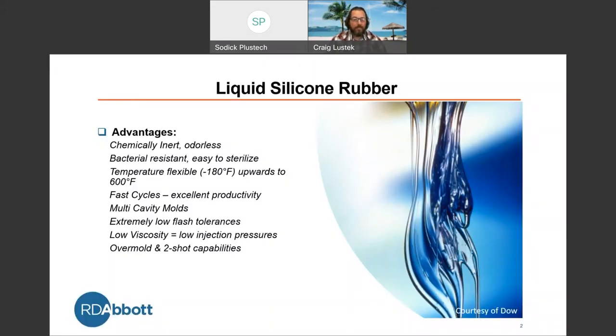Just a little overview for liquid silicone rubber, looking at your advantages, again, being chemically inert, odorless, bacterial resistant, easy to sterilize would make it very popular for running certain applications. The flexibility of temperatures from negative 180 Fahrenheit upwards of 600 degrees Fahrenheit. Your fast cycles, which allow multi-cavity molds, extremely low flash tolerances. And with those low viscosities of the material, we're looking at lower injection pressures. And when we talk about the low viscosity, that's the measure of the resistance of the material, where we can measure different centipoise of that material.